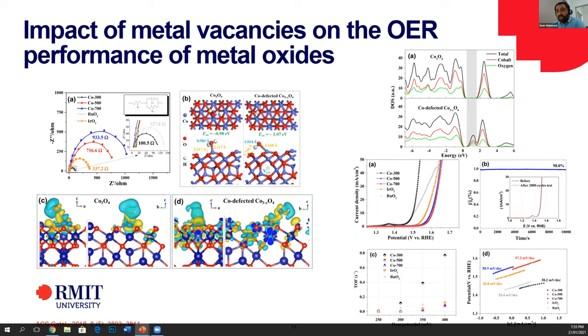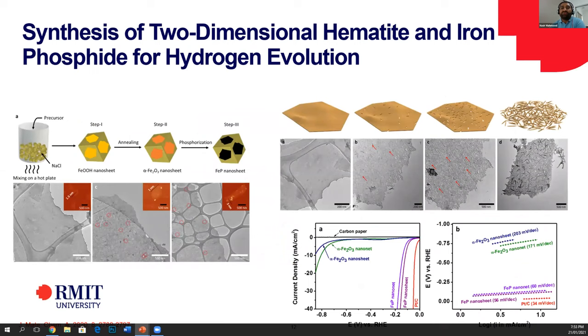But the oxygen evolution reaction is not the only part of overall water splitting. We also need catalysts that can do the hydrogen evolution reaction. For that, metal phosphides are very good. So we recently tried to develop something that has a very unique surface, because we need more catalyst sites to be exposed. So we developed some 2D iron phosphide, because transition metals are always good.